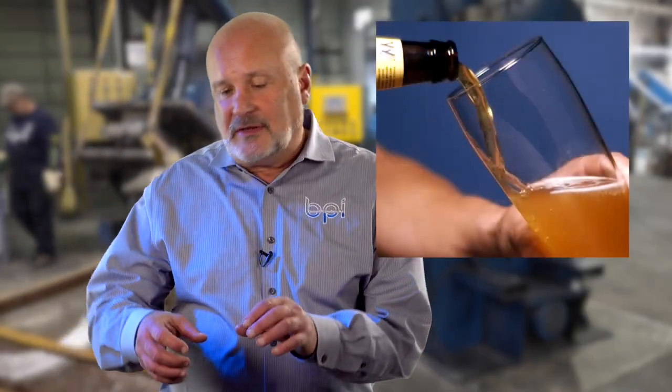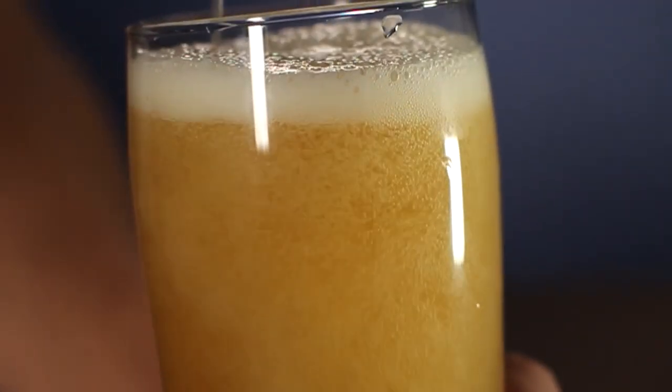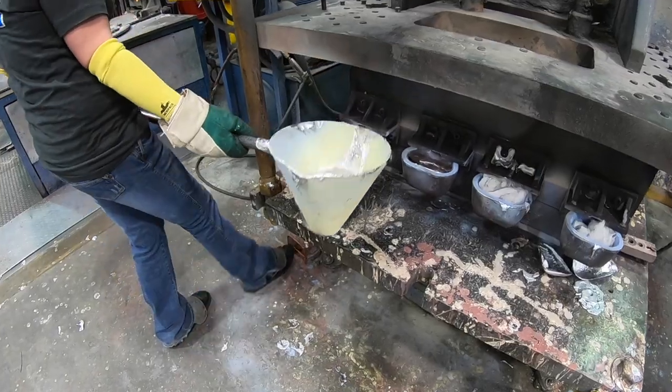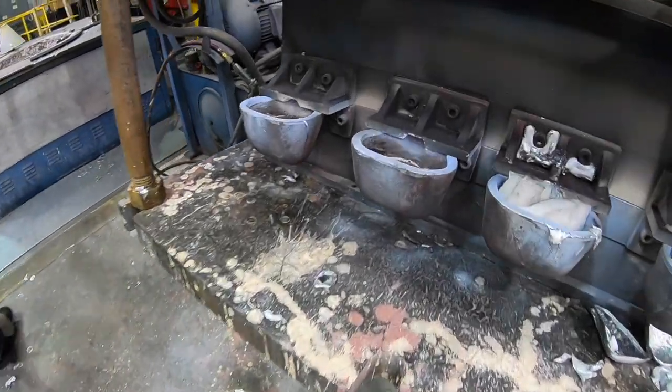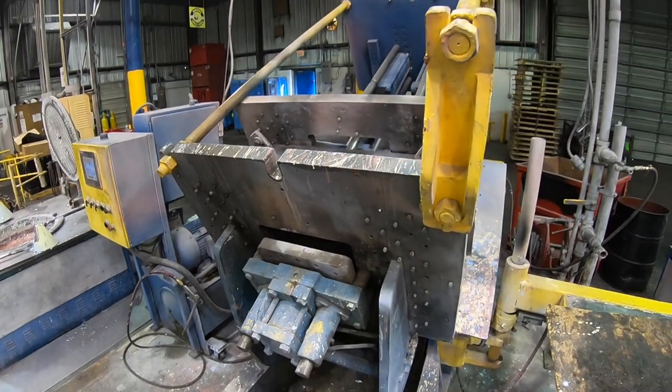Tilt pour is pretty easy to understand — it's like pouring a beer down the side of the glass. You get less turbulence, less head. Pour a beer down the center of the glass and you get turbulence and a big head of foam. The more turbulence you get, the more air pockets are created. You don't want that in your casting because that is gas, that's porosity. You don't get as dense or as hard of a part. It causes problems in powder coating, makes machining more difficult, makes the part weaker, and leads to failures.